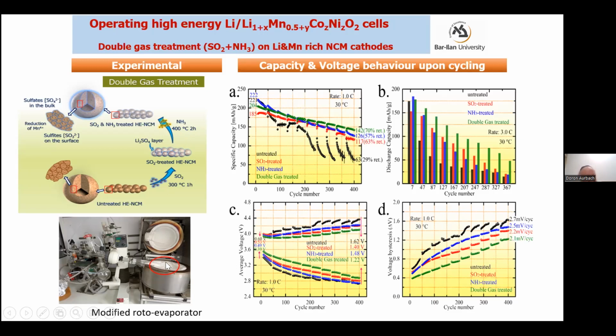And the operation is in an oven, going up to several hundred degrees centigrade in the appropriate gases. And we found that by double gas treatment, we start with SO2, and then we go further with ammonia, we have much better results than, of course, if we don't do anything, or we use only ammonia or SO2. So here you can see some results. In this chart here, this chart shows specific capacity at high rates. 1C rate is considered high, fully charged and discharged within an hour, which is not too bad. And we definitely see that the double treatment shows a better stabilization of the capacity.